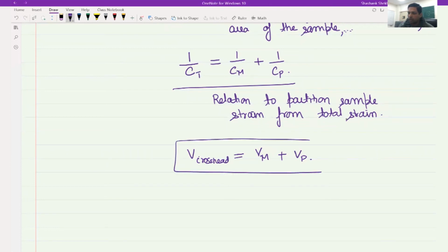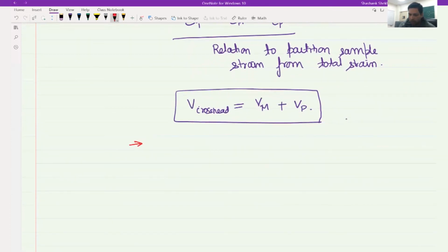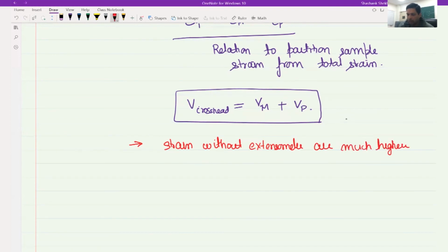So these two things together clearly tell us that the data that we obtain from the equipment has to be looked at carefully and understood properly. And if you do not carefully partition the data, you may get very erroneous data. For example, what you would observe is that strain without any external method of measurement, so if we are using only the crosshead for measuring the strain, without an extensometer, the strains are much higher. That we can obtain from our relation over here.